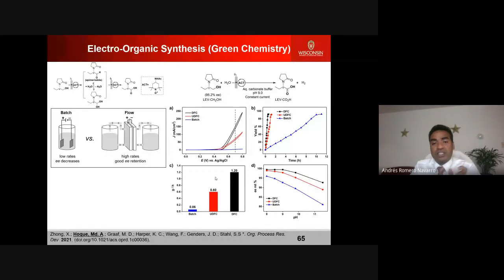And as I was saying, we must also consider the stereochemistry, and the black one I'm showing is the divided cell. We can see that at pH between 8 and 9, the stereochemistry remains intact, which was not the case in the batch cell or the undivided cell. So we developed a very efficient method for making the chiral carboxylic acid.